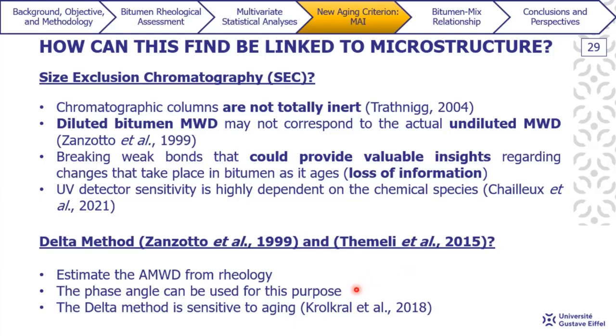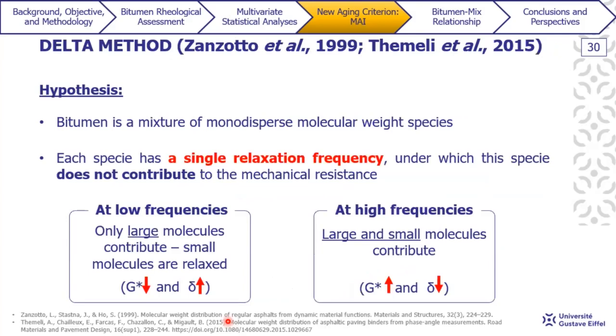And for this purpose, the phase angle master curve has been used. And the delta method has proven to be very sensitive to aging in some previous publications. So the hypothesis on which the delta method is grounded is pretty much seeing bitumen as a mixture of monodispersed molecular weight species, where each of these species has a single relaxation frequency under which this species does not contribute to the mechanical resistance. So here we have two different situations.